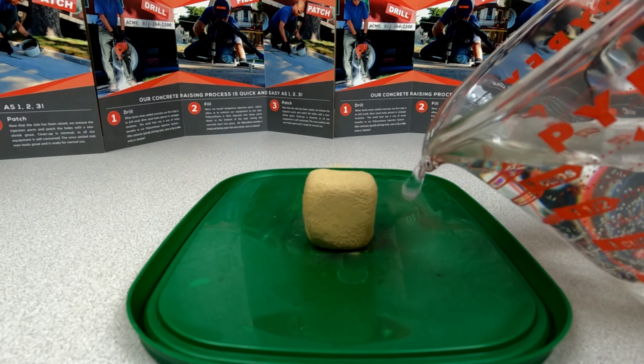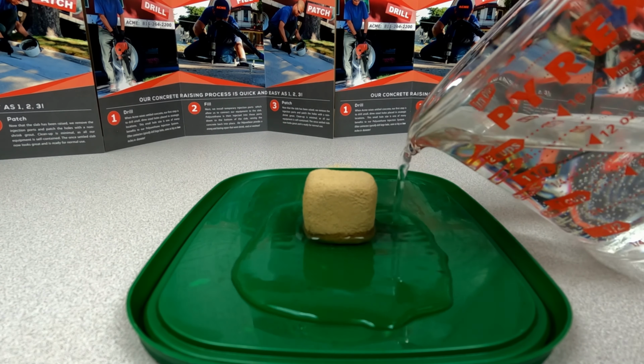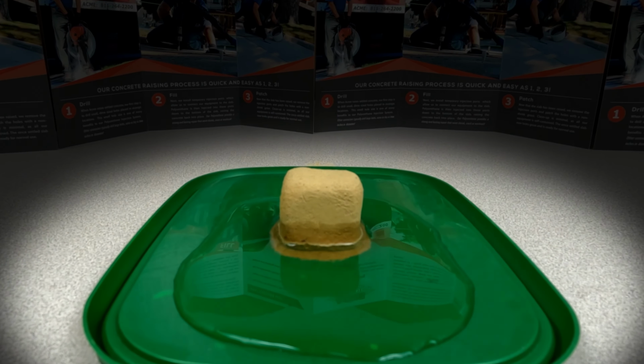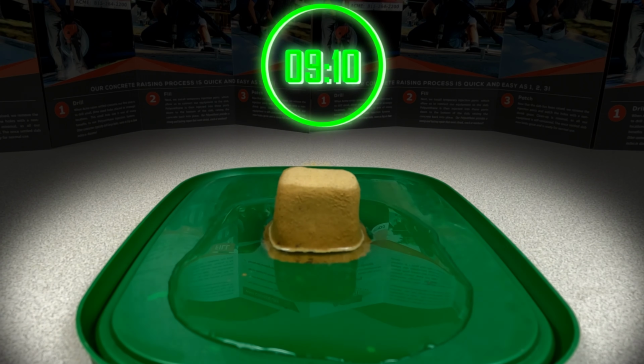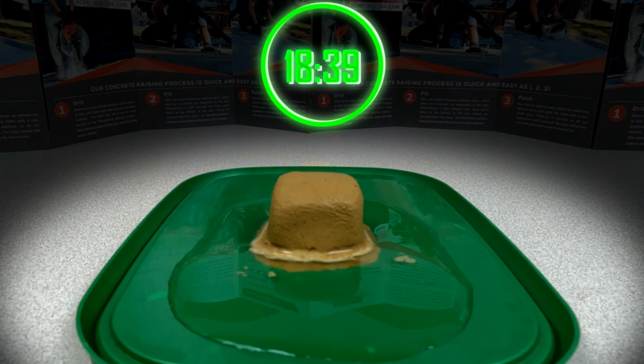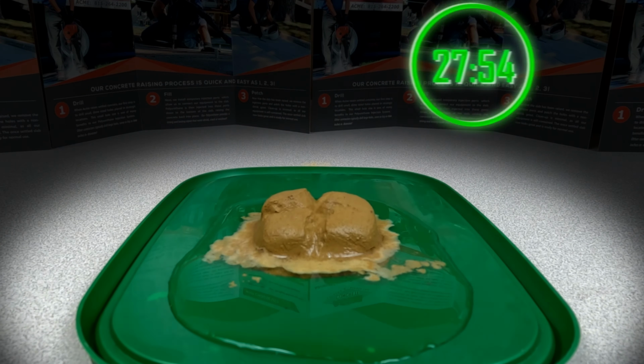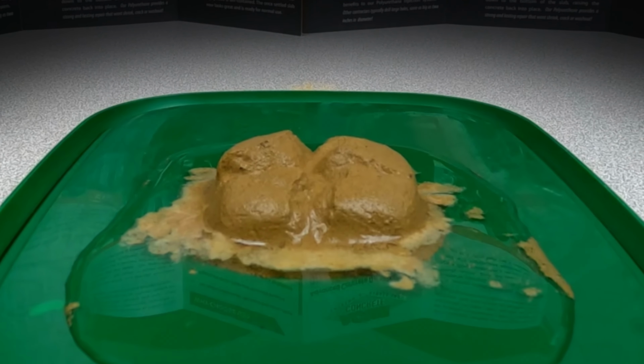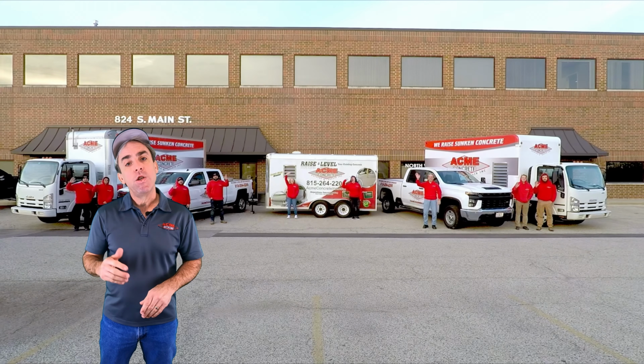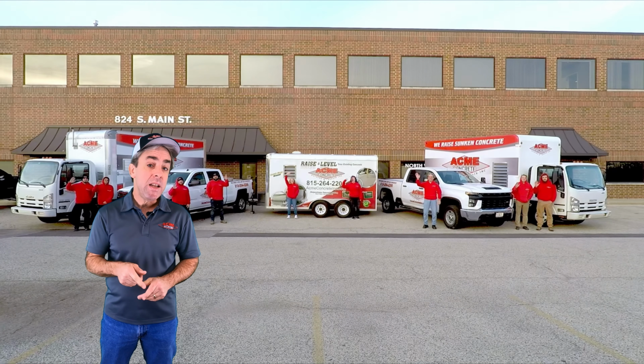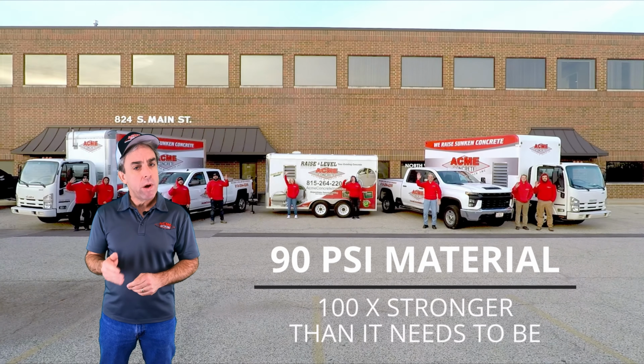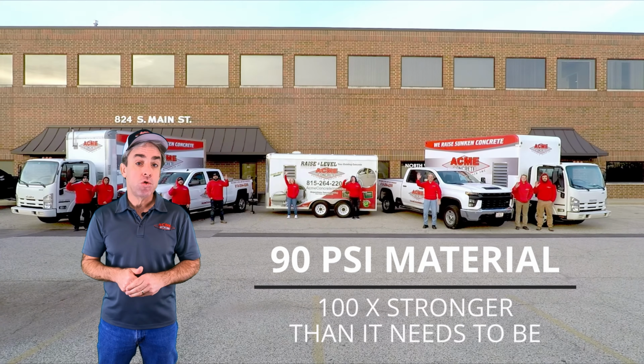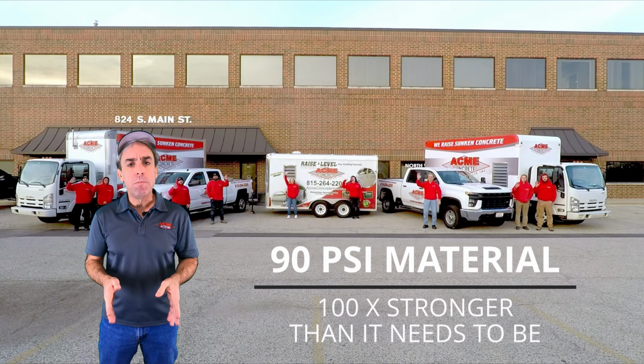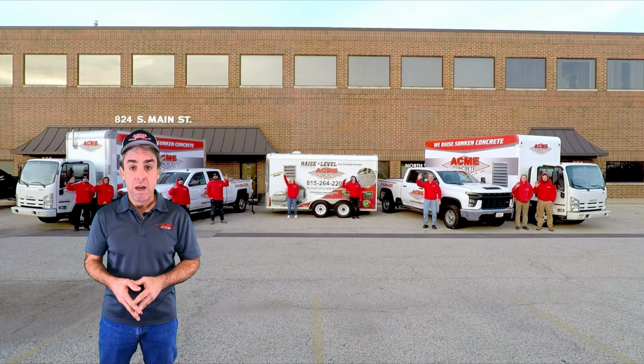Not only did the material fail to resist water, it absorbed the water like a sponge. In less than 30 minutes' time, the sample returned to its original state, mud with no compressive strength at all. You might find it hard to believe, but our 90 psi material is theoretically about 100 times stronger than you would need it to be for any practical application.